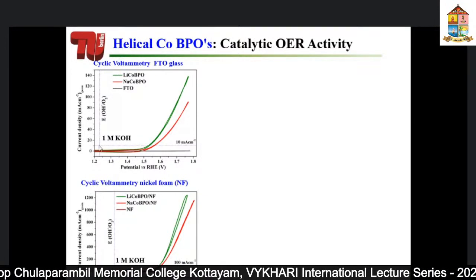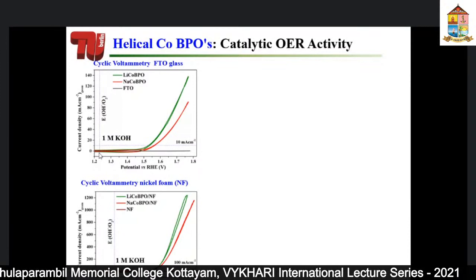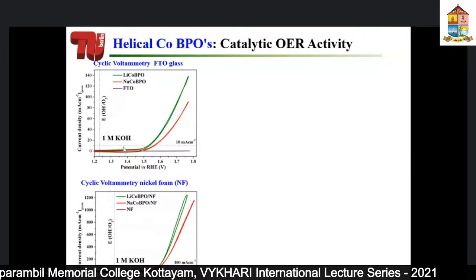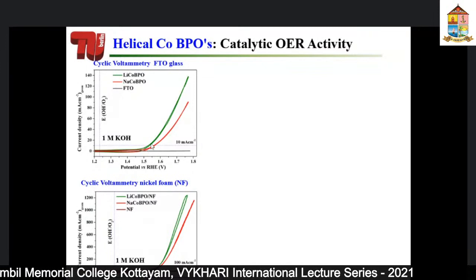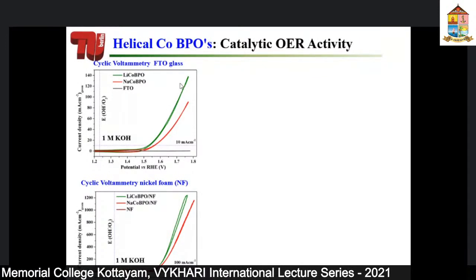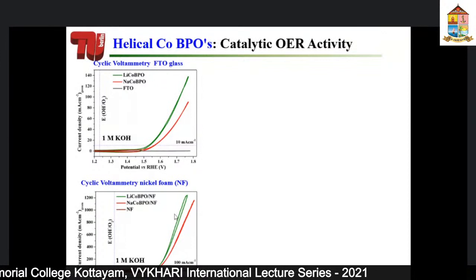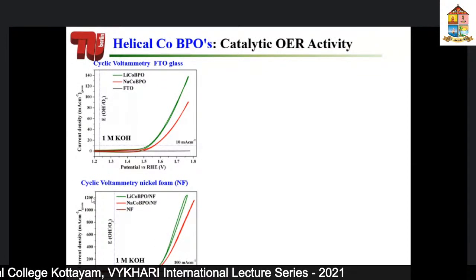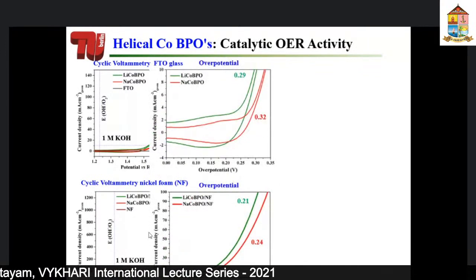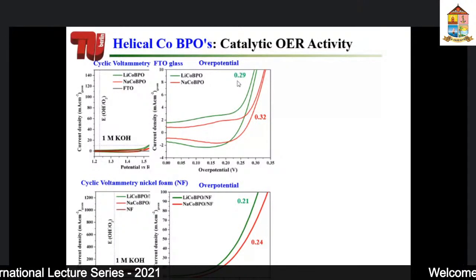And if you apply the potential from this direction, you would see that you have oxygen evolution at around this particular area. Similarly, if you take nickel, this is even faster, you attain much more current than FTO, because this is much more conducting. What is important, I told you, is the overpotential. So how much extra potential one needs to apply, which is also determined by these curves. You could see that we need almost 290 millivolt extra potential to have oxygen evolution reaction.